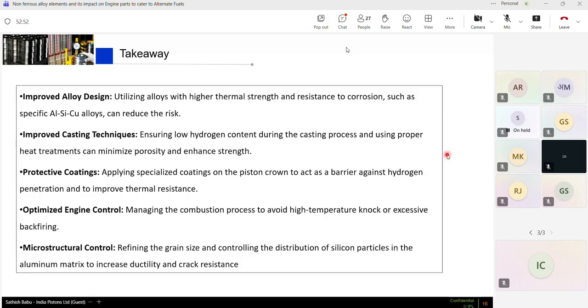Of course, we also use some amount of low hydrogen. We have a hydrogen content running inside the casting process, and we use proper heat treatment. So we are trying to ensure that low hydrogen content is used in the casting process, and this will be helpful, and also minimize the porosity levels. Generally, this